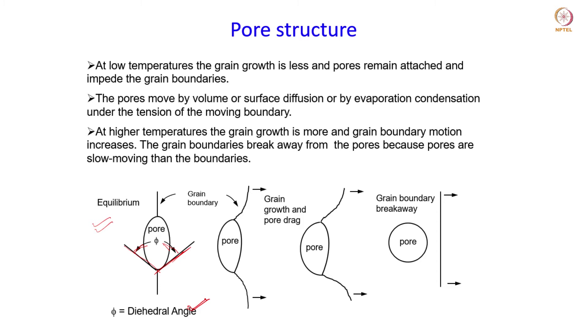That is how the interaction between the pores and grain boundaries starts. There could be two things happening: the pore will get dragged along with the grain boundary as the grains grow during sintering, or they might break away. As you can see, the pore is sitting on the grain boundary, and as grain growth occurs through the migration of grain boundaries, when the pore is sitting on the grain boundaries they will also move but may break free.